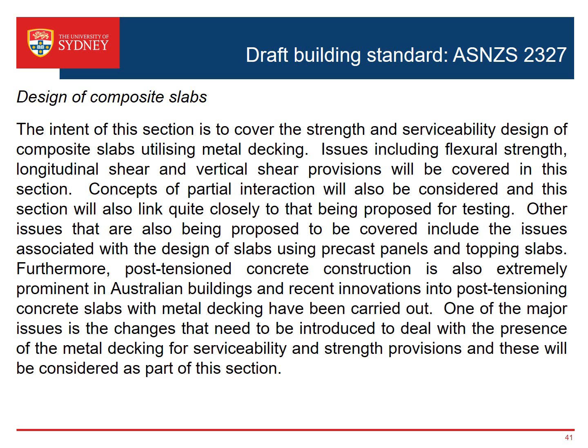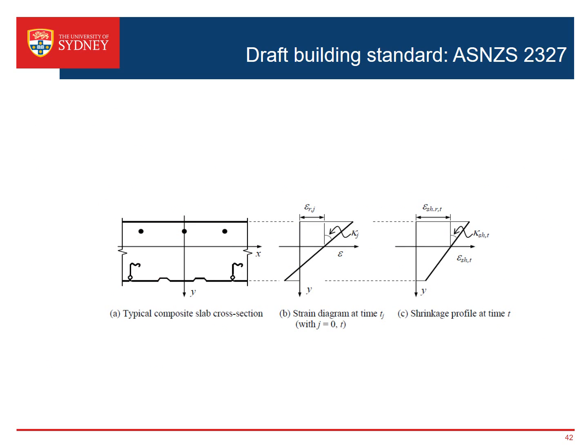So just going through some of the issues, one of the issues was actually led by one of my colleagues at the University of Sydney, and this is a phenomenon that we looked at quite a number of years ago. If you look at a traditional concrete slab, you've got a free surface here which is exposed to the atmosphere. Let's assume you don't have the decking here, and it's a concrete slab. Again, you've got this bottom surface that's exposed to the atmosphere. You get, if you like, moisture travelling out at the top and the bottom of the slab. When you look at free shrinkage in a concrete slab, you should actually have a constant shrinkage value throughout the entire depth. Now the problem that arises when we have metal decking is we get the moisture loss through the top, there's zero moisture loss through the bottom.